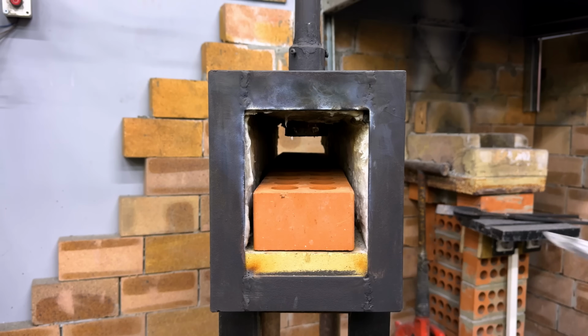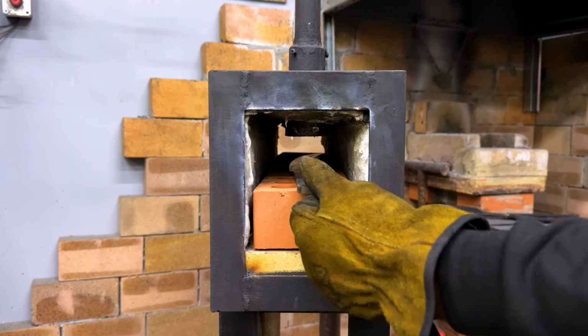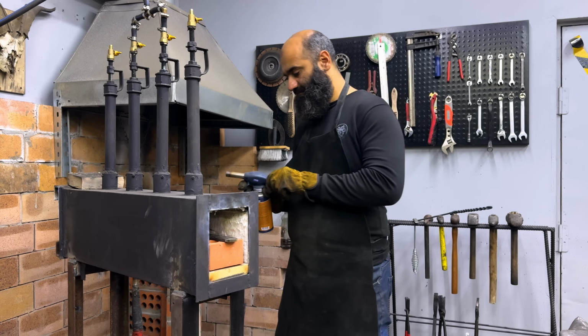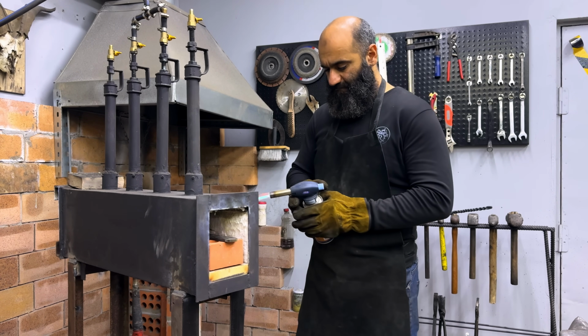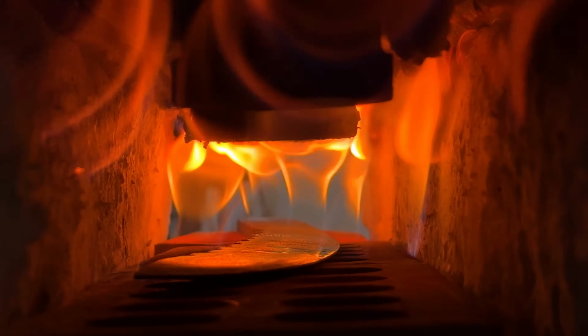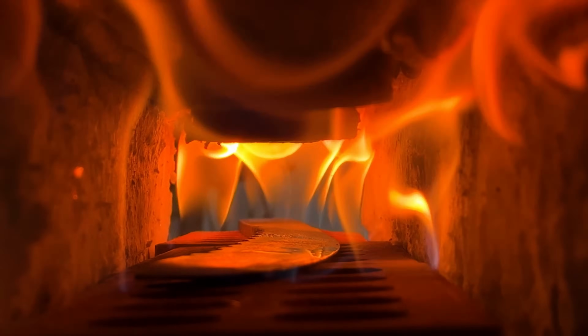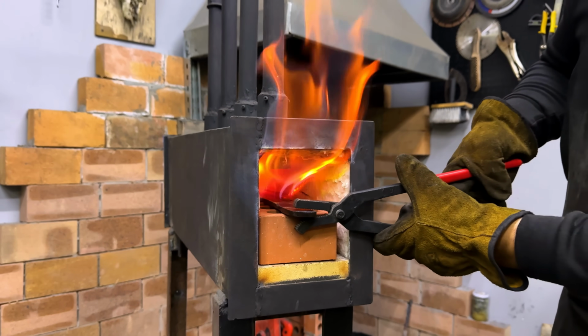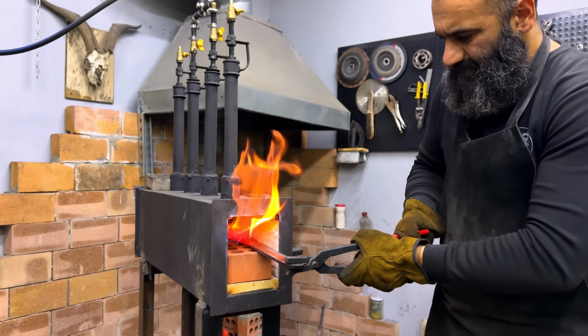Heat treat time. This is the most critical step. I'm using the long gas forge to get an even heat across the entire length. We need about 840 degrees C into the oil. Listen to that sizzle. We are locking the carbon into the crystal structure, turning soft steel into hard martensite. No warping allowed. Hold it straight until it cools.